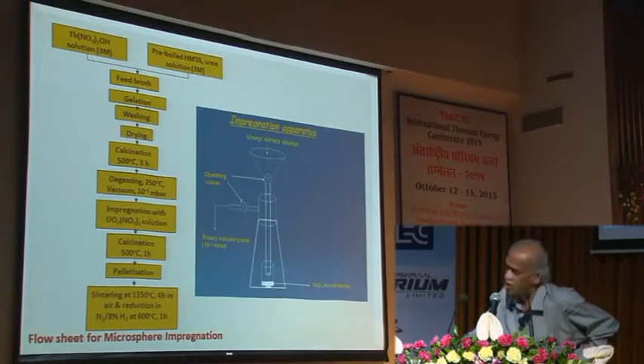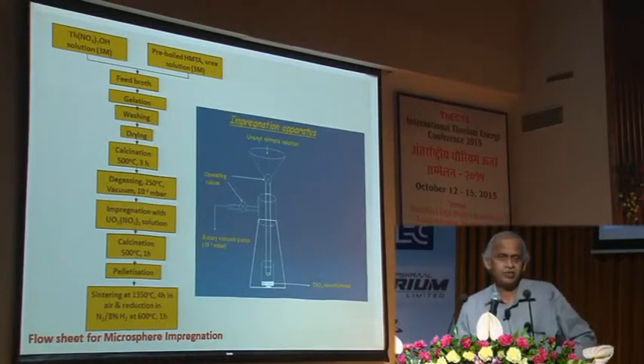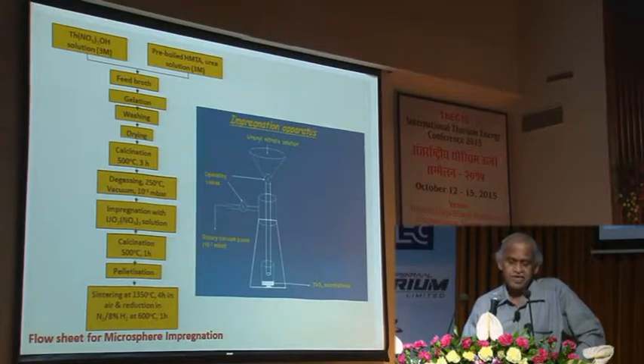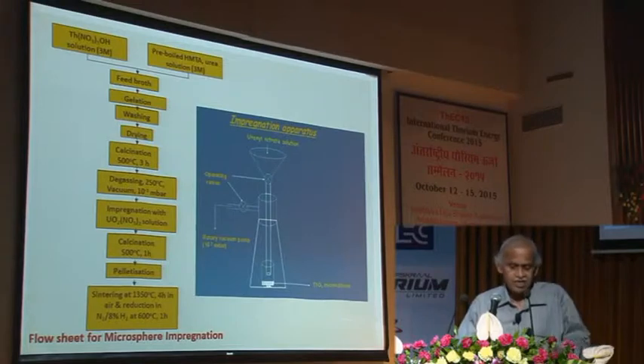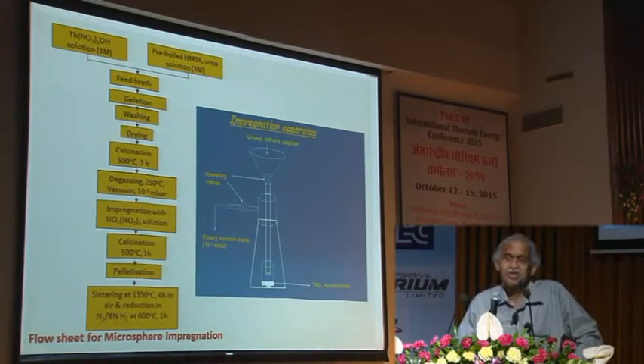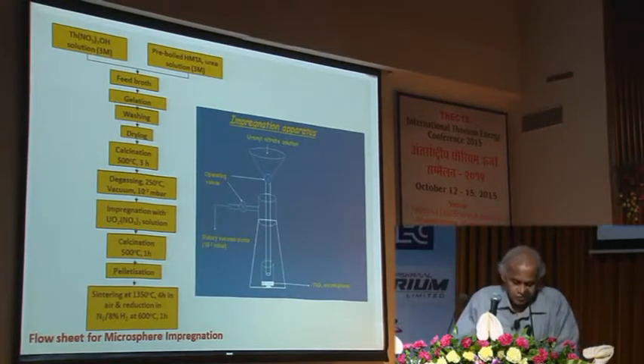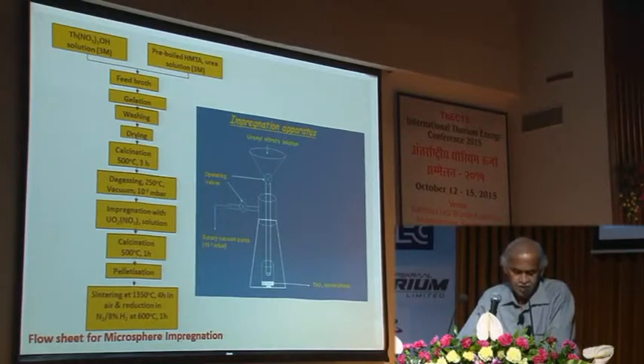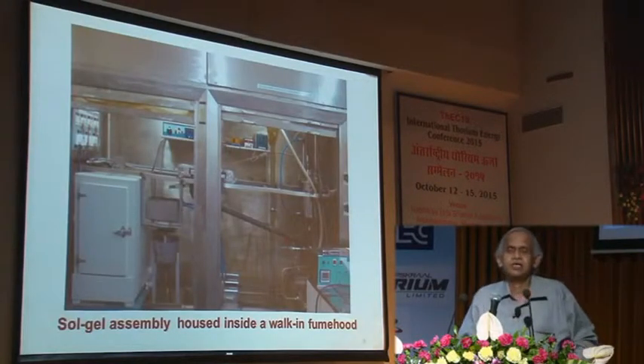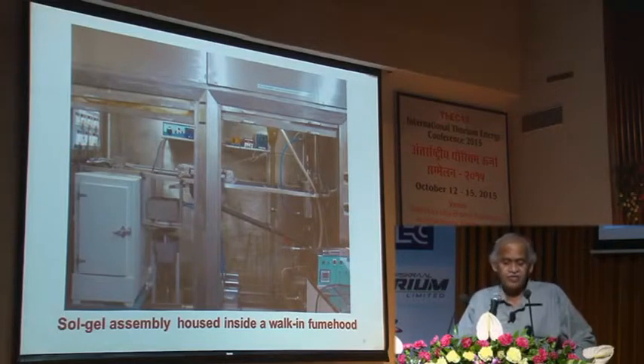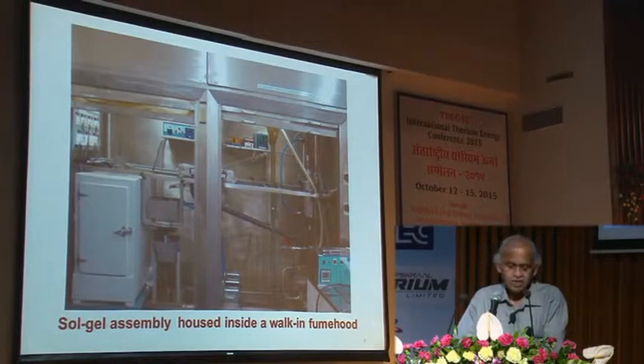This is the flow sheet we normally follow. First we make the thorium oxide pellets, and then we go for the impregnation technique with uranyl nitrate, and ultimately we sinter at 1350 degrees Celsius for 4 hours in air, and of course reduction in nitrogen hydrogen atmosphere at 600 degrees Celsius. This is the walk-in glove fume hood facility which is being operated to make these thorium pellets, and then of course later on we go in for glove box for